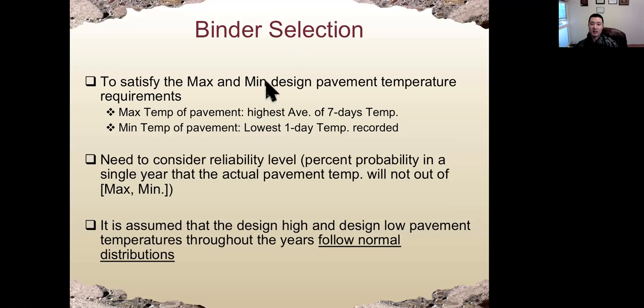So to satisfy the maximum and minimum design pavement temperature, we need the local history of temperature. Okay. So the maximum temperature of the pavement will be the highest average 7-day temperature. Okay. But the minimum temperature of the pavement will be the lowest 1-day temperature recorded. Okay. And we also need to consider the reliability level, which is the percent probability in a single year that the actual pavement temperature will not be out of the range of maximum and minimum temperature. Okay. It is also assumed that the design high and design low pavement temperatures will follow a normal distribution.